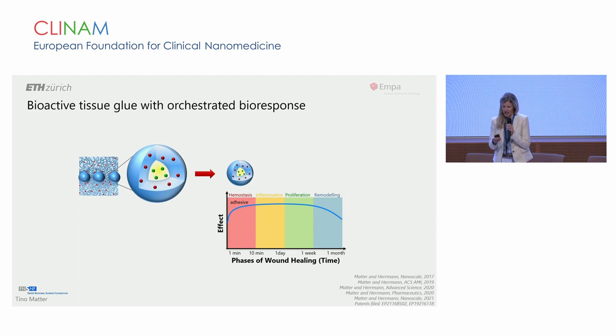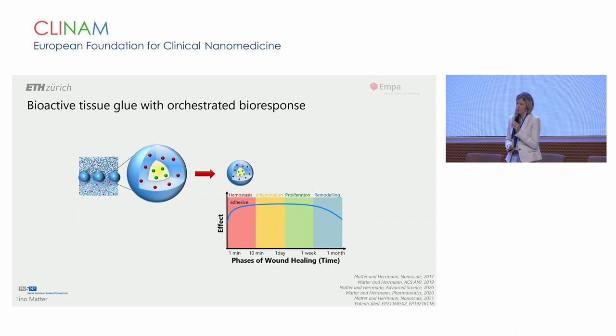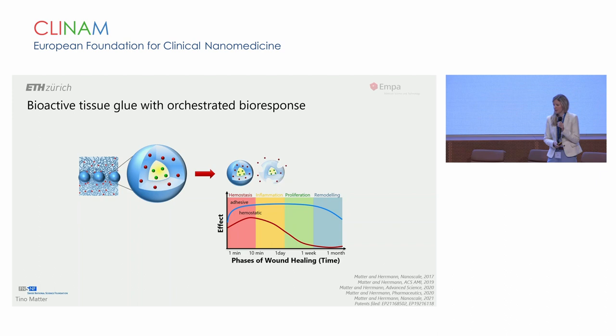We imagined that by having a core-shell architecture with a shell that would interact with the blood coagulation system, adhere to tissue, then gradually dissolve, release ions, and reveal a core that would then take additional functions, such as anti-inflammatory activity or antimicrobial activity.